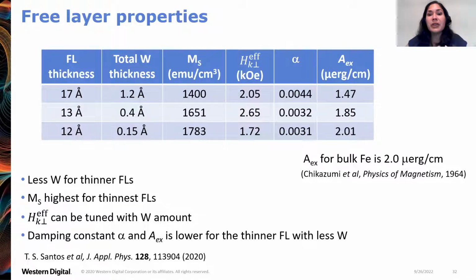Yeah, I'm definitely aware of the studies that do show that as you get to very thin layers, the damping parameter actually goes up. And so this was something we were looking out for in our study, and we are fortunate to see that here, even when we're very thin, the damping value is still low. However, if you do go lower than this, you start to see it go up.